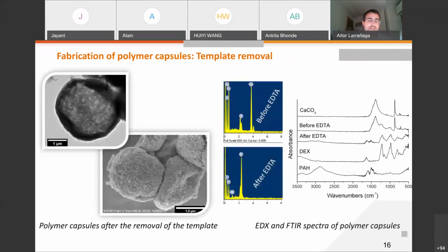Then after this layer-by-layer approach, after coating our sacrificial template with the polymeric layer, we proceed with the removal of the template. As you can see in this scanning electron micrograph, some of the capsules appear collapsed, which is quite characteristic of this kind of hollow capsules. And this happens due to the high vacuum that is used for SEM observation and indicates the successful template removal.